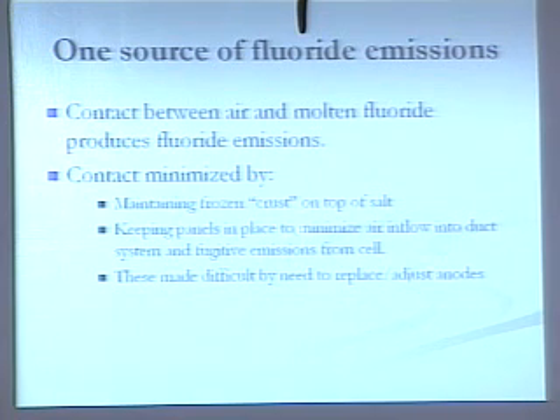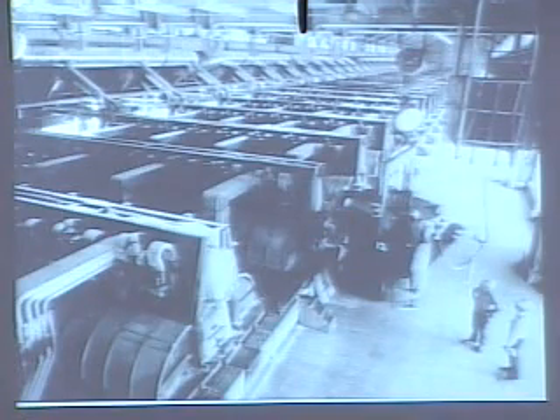Another good way of minimizing the fluoride emissions is keeping these panels in place that I pointed out to you. Those panels are there so that the gases which are generated in the cell are sucked off the cell through some ducts, which I failed to point out to you, but I will go back to. So over at this side of the cell are these ducts leading into this big duct here, which is under vacuum or reduced pressure, so it sucks the gases into a gas cleaning system.